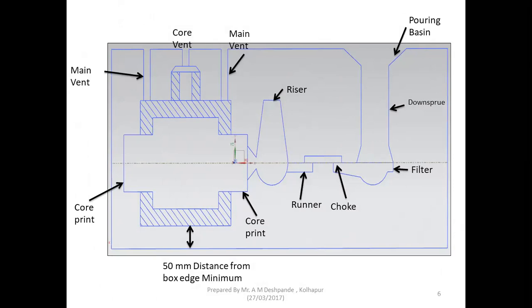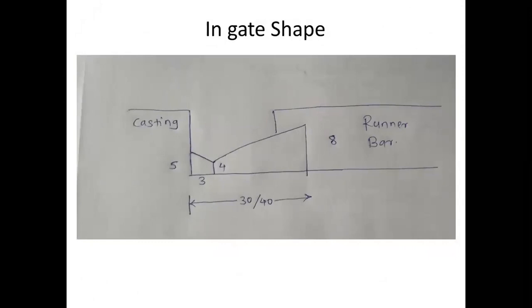to know the casting height in cope box, riser height, some terminology: choke, runner, filter, core print, main vent. Main vent means the mold gases, and core vent means core gases. Standard terminology. In case of cast iron, basically ingate thickness will be 5 mm, then notch will be 4 mm, distance from casting will be 3 mm, distance from runner to casting should be around 30-40, not more than that. That is also equally important.